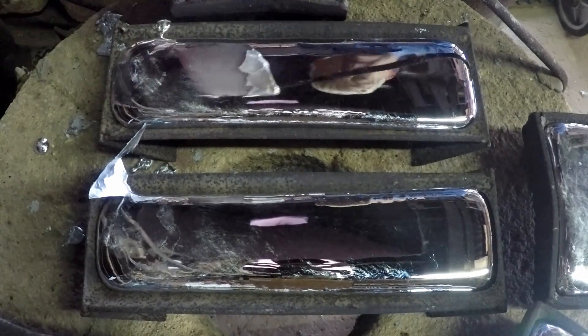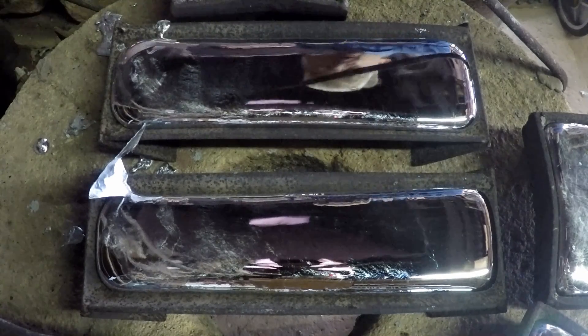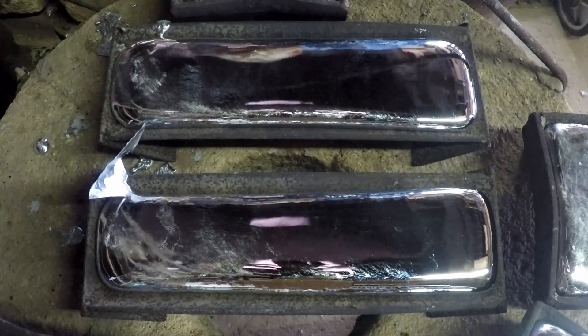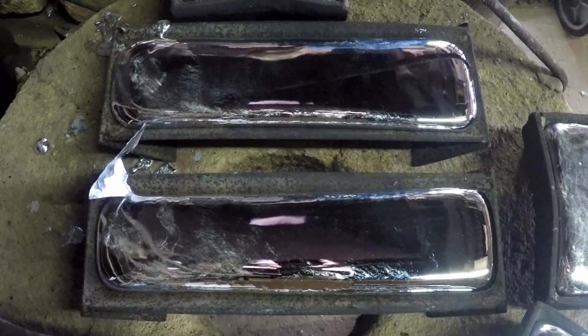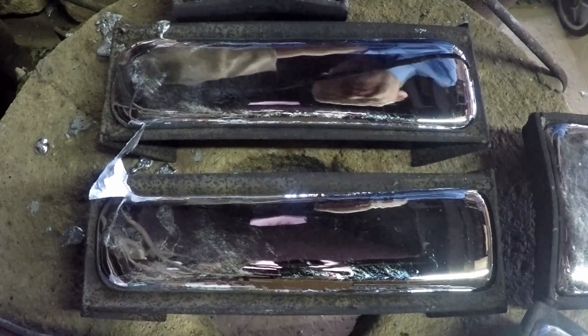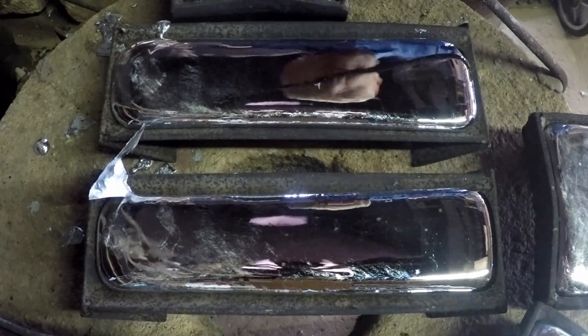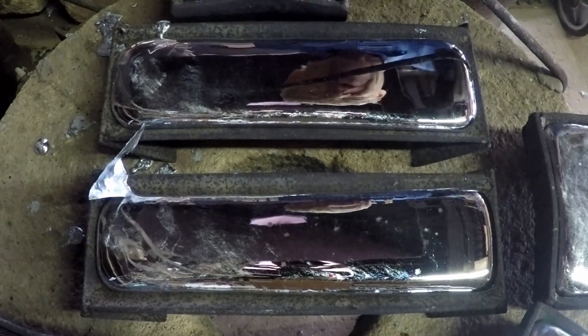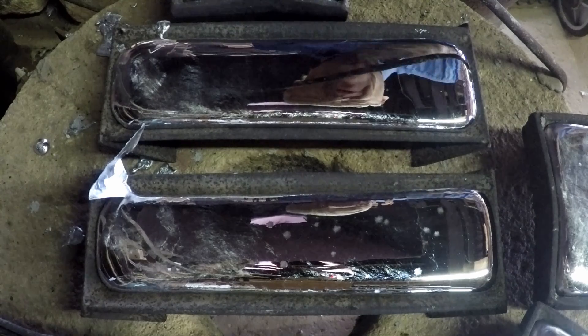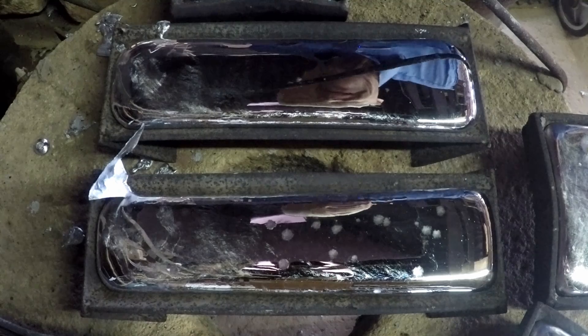I observed last time that little areas in the middle of that shiny surface suddenly developed, and the eutectic cells grew from them right in the middle of the shiny bit. This I thought was quite strange, and here it is happening again — you can see these dull areas growing. The eutectic cells are not growing from the cool mould edge; they're just growing from in the middle of the metal.